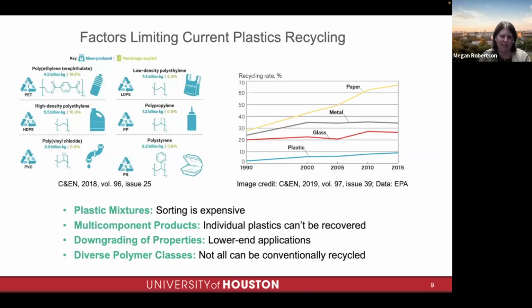But focusing a little bit more on the technology, one limitation is the fact that right now we're sorting all the plastics into different streams because they're essentially incompatible and don't want to mix. And in order to have a higher quality resin coming out of the process, we need to remove as many contaminants as possible. That also includes things like additives, which are now being combined in very non-ideal ways in the plastic streams. And this can all lead to a general downgrading of properties when you compare the recycled resin to the pristine resin.